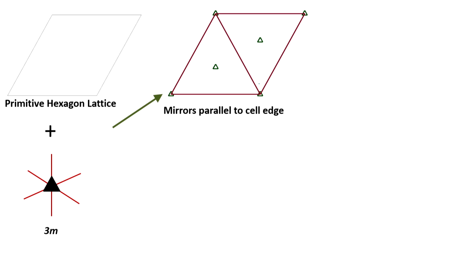Let us consider the mirror plane, and let me call this M1, the one on the short diagonal. Now, what would happen if I did a reflection operation sigma 1 across mirror 1, followed by a lattice translation? Two of the lattice translations are A bar and B bar along the two edges, so followed by A bar. Now, this translation is at an angle, so we probably expect that there would be a glide plane somewhere.